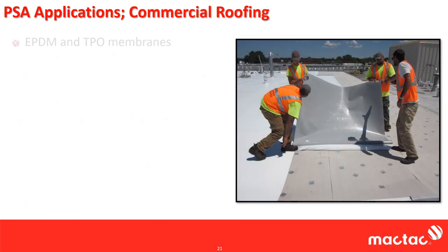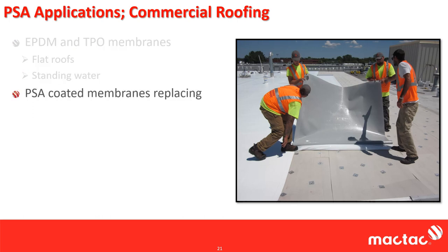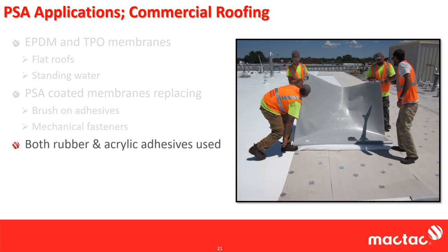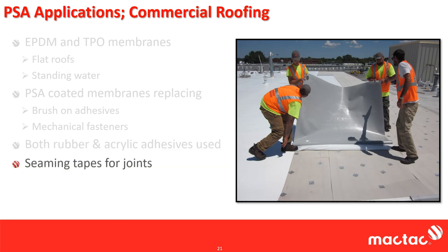In commercial roofing, where a lot of EPDM and now TPO membranes are being used, these are typically flat roofs that have standing water, PSA-coated membranes are growing in popularity. They are replacing the need to apply structural adhesives at the job site for simplicity and increased productivity. And with these types of roof systems, you want to reduce or eliminate mechanical fasteners, which create entryways for water. Both rubber and acrylic adhesives are used for various reasons, and MacTac offers some very unique options for this market that combines the best of both worlds. PSAs are also used in seaming tapes for joints with these types of roof systems, and for patches when holes occur.